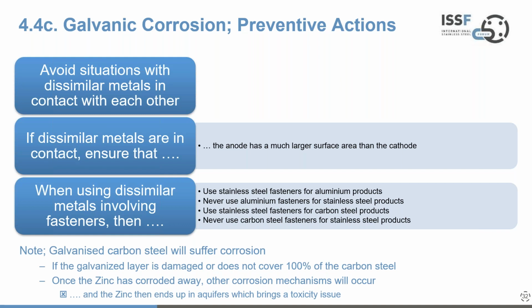But as a point of note here, galvanized carbon steel, whilst it will resist corrosion rather well, will suffer corrosion if the galvanized layer is damaged or does not cover 100% of the carbon steel. Once the zinc has corroded away, you'll start to get other corrosion mechanisms occurring on top of that. So it is a note of caution. And then the worry is here that zinc ultimately ends up back in aquifers, and it's a toxicity problem. Zinc is not an inert metal in its own right. So just a note of caution to be aware of.